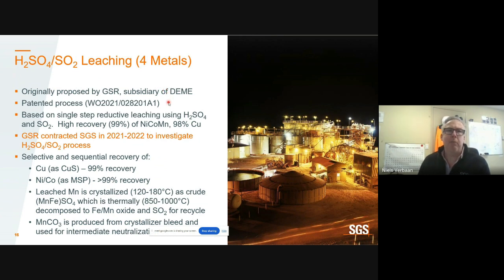It's a single-step reductive acid leaching route using sulfuric acid and SO2 gas, characterized by high recoveries of all four metals. We were contracted by them in 2021 to investigate this route, and we've shown that we were able to get high recoveries: 99% nickel, cobalt, manganese, 98% for copper.